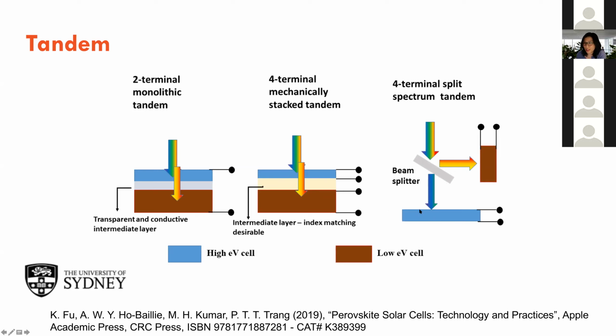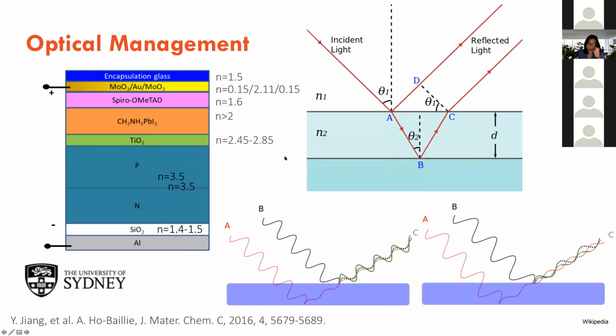So this, in terms of integration, is the easiest, but you can have optical losses through these optical elements, and also you just have all these extra wires dangling out. But on the left-hand side, the integration is the hardest, but it's the most elegant in terms of the wiring coming out. You only need to worry about one pair of wires. So in my lab, we're interested in the monolithic integration of tandem cells. And as you can see, when you stack layers with different refractive index, you run into a problem of constructive and destructive interference. The worst case is you don't want the reflected light to interfere with each other in phase, and then you get really large reflection, what they call Fresnel reflection.